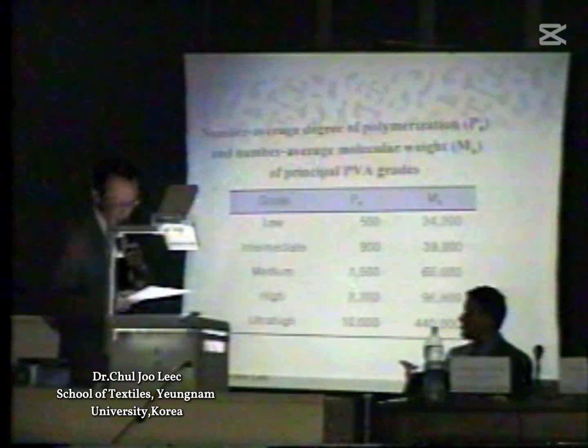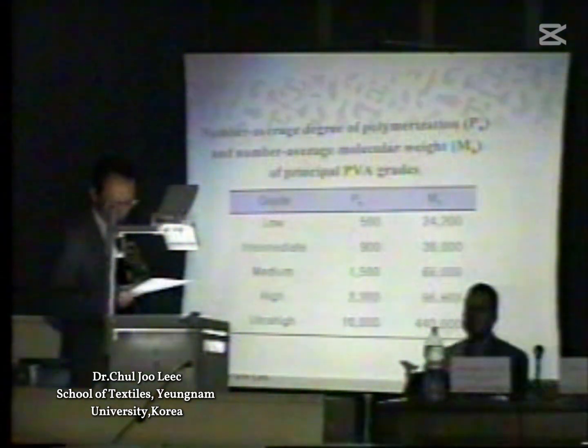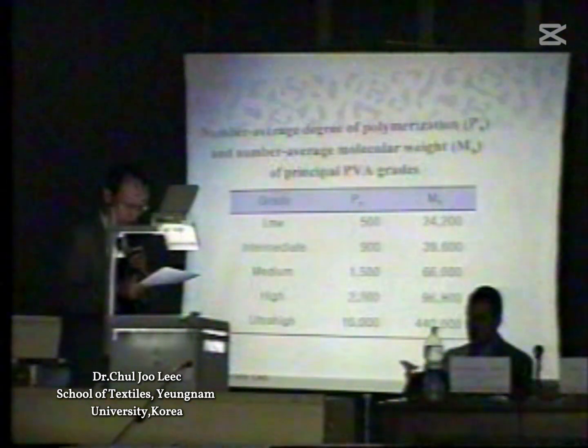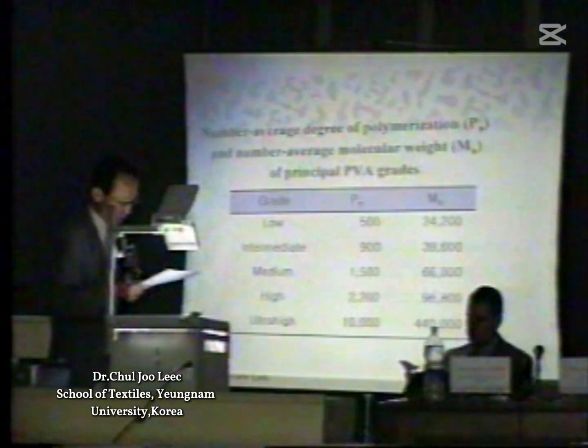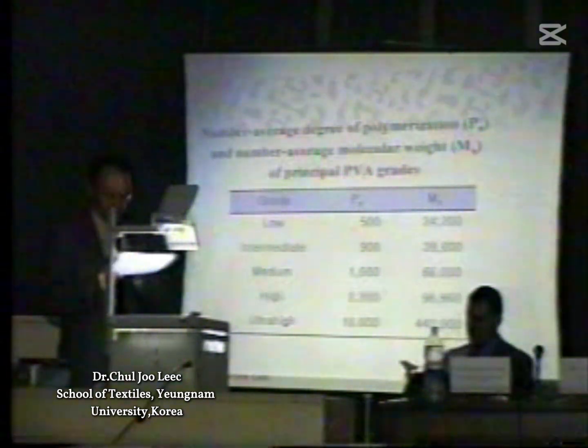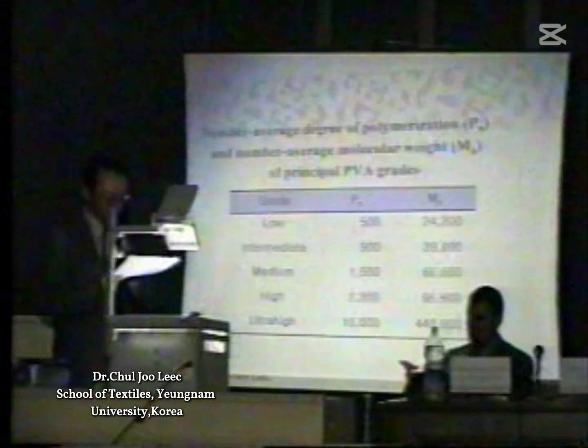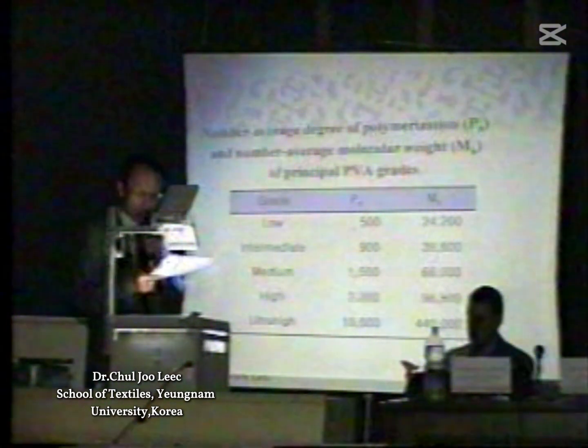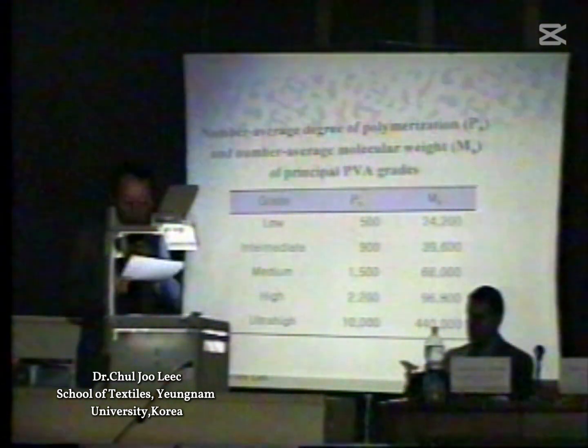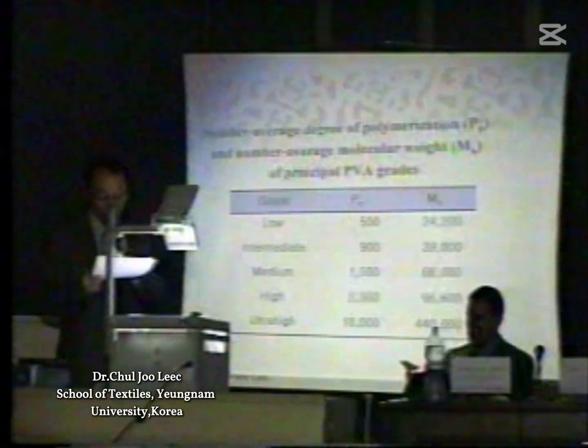This is the typical aspect of polyvinyl alcohol. The molecular weight is from 24,000 to 440,000, and the number average degree of polymerization is 500 to 10,000. The fibers from this polyvinyl alcohol have high tensile and compressive strengths, high tensile modulus, and high abrasion resistance. However, there are still many attempts to enhance these mechanical properties. To maximize the properties, we should control the molecular weight, the degree of saponification, and tacticity. We call these the molecular parameters.